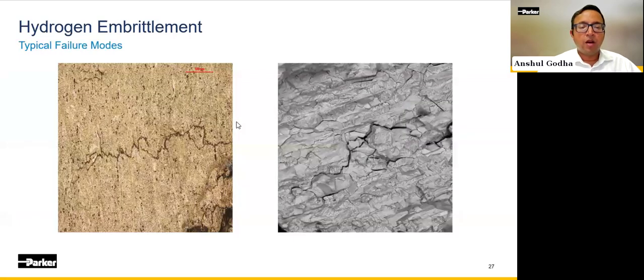This is what a typical hydrogen embrittlement crack looks like. While it is possible to have hydrogen embrittlement cracks that are both intergranular and intragranular, the more common method of cracking here is the intergranular cracking, which is shown in these two images.